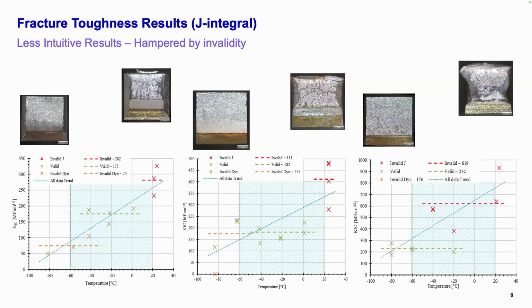Highlighting there the range in which all of them went through from that transition from brittle to ductile. The only one that's actually looking quite useful is the pre-cracked one, the one in the middle. So the side grooved ones, even though they have slightly more valid tests where we talk about traditional fracture mechanics, the dynamic instability is coming into effect there. So there's even less useful data coming out of these tests. The useful range, green, is the area where I can be very happy with the tests that we've got, and that the standard methods of fracture mechanics come into effect.